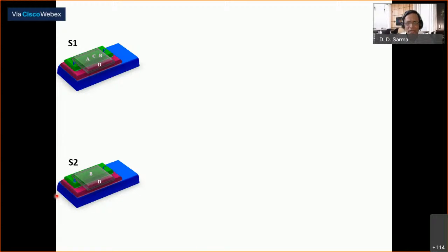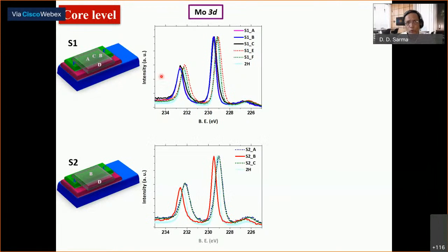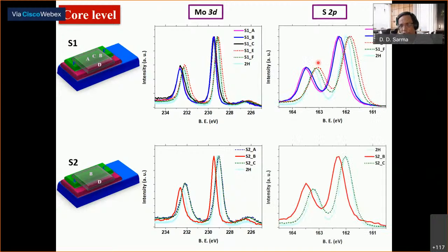There are two samples. I'll only show you this S1 sample and not the other sample, because it is the same information. We find that whenever we choose A, C or D, which is the heterostructure, molybdenum disulfide, I'm looking at the molybdenum 3d signal under the graphene, it is the solid lines. Whenever I look away from the graphene, E and F, these are the dash-dotted lines, they're at a lower binding energy. And it doesn't matter whether you look at molybdenum 3d or sulfur 2p, it's exactly the same description.